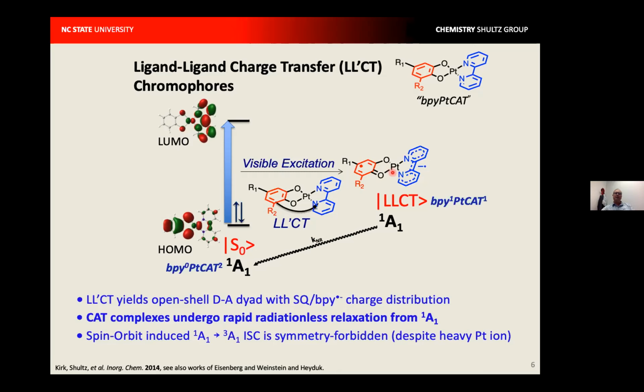The catecholates here turn out to be key, because this singlet excited state, this ligand-ligand charge transfer excited state, despite the presence of the platinum, is a short-lived singlet excited state where intersystem crossing is forbidden by symmetry. And so these do not fluoresce, they do not intersystem cross. For all of the derivatives that we've studied, in under 1 nanosecond, they decay non-radiatively back down to the ground state. And as I'll show you, that turns out to be key for our spin polarization studies.